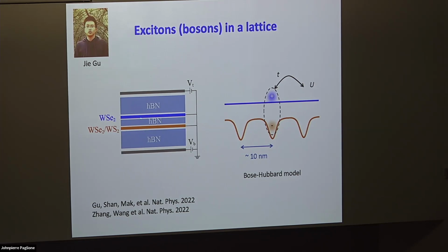Yeah, so for these materials, we don't need the glove box. They are very stable. But if we are dealing with molybdenum ditelluride, you need a glove box to do that. And actually, that's the part I did not talk about, that we use the tellurium to generate these topological bands, because we need that to tune the band alignment, right? And so for that, you do need to do everything inside a glove box, which is a pain in the neck, yeah, but you have to do it in order to keep the material alive.